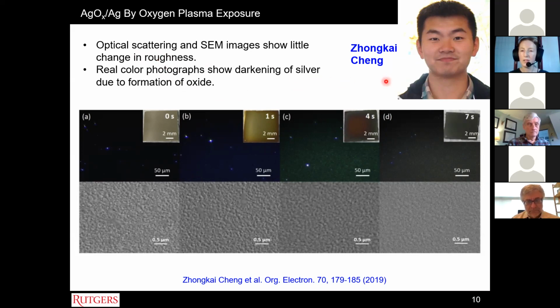So one of my PhD students, Zhongkai Cheng, in a recent study, looked at the performance of silver oxides on silver made by low power oxygen plasma exposure of silver on the performance of F8BT hole only devices. This is some of the optical and morphological characterization. You can see as we increase the oxygen plasma exposure, there's a little bit more scattering, and this means that they're slightly rougher, but overall the increase in scattering isn't that significant. And you can see from the SEM, the morphology is relatively good. It's a relatively smooth surface. You can see though from the real color photographs, there's a darkening of the silver due to the formation of oxides.